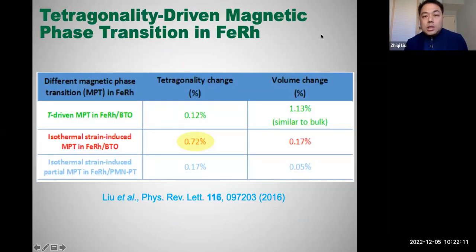We also try to compare the mechanism for different phase transitions between the temperature-driven magnetic phase transition in iron-rhodium and the isothermal piezoelectric strain-induced magnetic phase transition in iron-rhodium. We found for this piezoelectric strain-controlled one, electric field-controlled one, the dominant mechanism is the tetragonality. That means the symmetry of the material. As we know in solid state physics, symmetry decides everything. For example, its electrical properties, magnetic properties, optical properties, and also some others, even thermal properties. So symmetry is everything for solid state physics or for condensed matter physics. So the piezoelectric strain control of magnetization is predominantly from the tetragonality change.